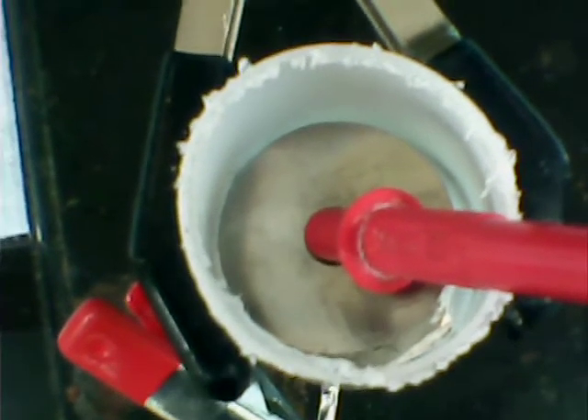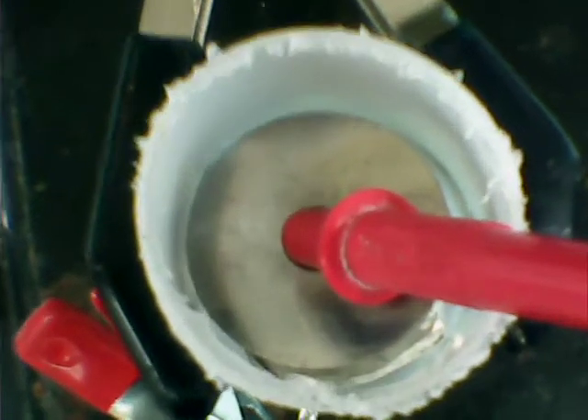I have on the bottom of the base — you can't see it here — but a piece of aluminum foil for contact. And you can't see the membrane on the bottom, but I have a starch electrolyte with chitosan, and a membrane at the bottom which separates the aluminum from the activated carbon underneath that stainless steel plate. That membrane is a thin film made from gelatin and some glycerol plasticizer — not soluble, at least right away, in water. And that's what I'm using on the bottom, not paper toweling.